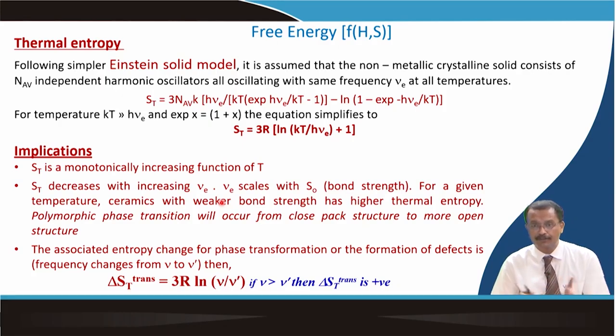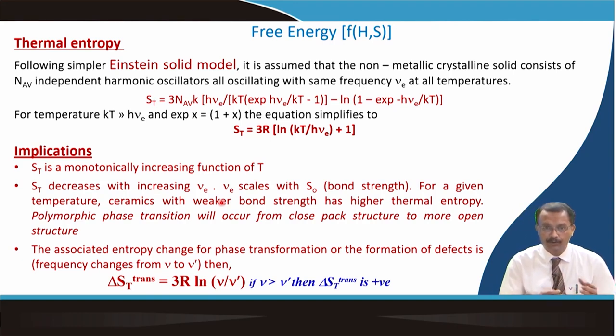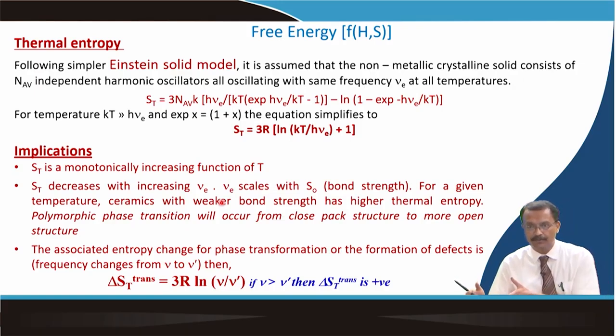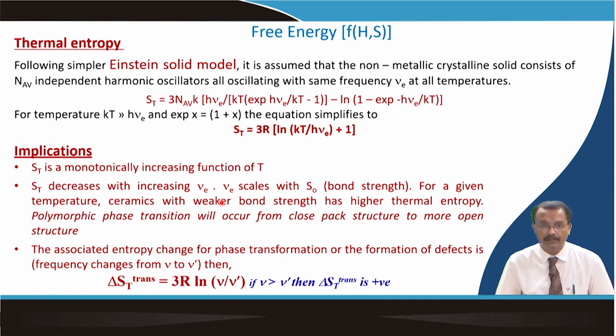So, you know, a polymorphic phase transformation occurs from one crystal structure to another crystal structure without changing the composition. Usually, it occurs from a close-packed structure to a more open structure. In the case of zirconia, a monoclinic to tetragonal phase transformation occurs. The associated entropy change for a phase transformation, or particularly the formation of a defect, is due to the frequency change from say nu to nu dash. So, this change in entropy is given by this relation, 3R ln of the ratio of the old and new nu values. So, as you can see, if nu is more than nu prime, then this transformation entropy is always positive.